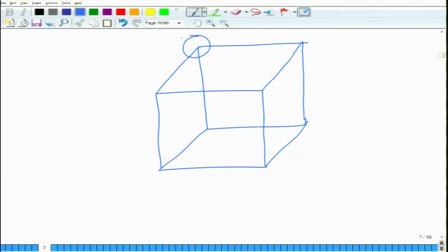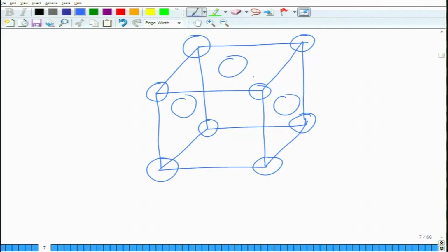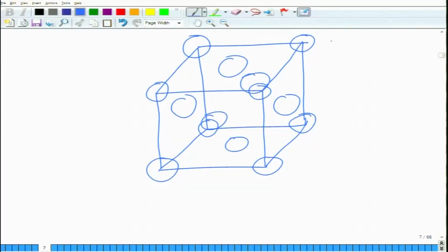So, first you fill X, this is X atom. These are all X atoms. Okay. Now, you have to draw the M atom. Tetrahedral voids are located at 1/4, 1/4, 1/4 type of positions. Basically, they are near the corners. Now, this atom has FCC structure with 4 X. Okay. How many tetrahedral voids do you have? You have 8 tetrahedral voids.